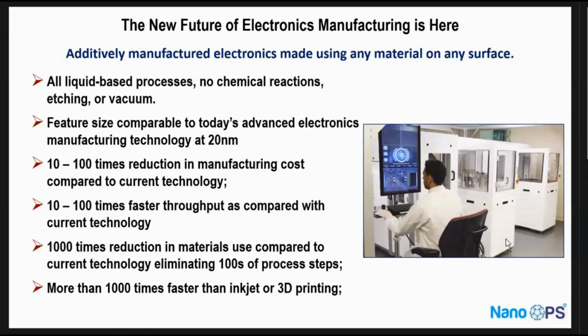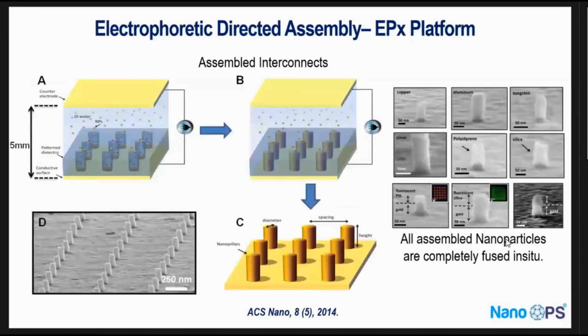It's about 10 to 100 times cheaper. It's about 10 to 100 times faster than conventional fabrication, for example. And it's about 1,000 times faster than typical inkjet or 3D printing techniques. In other words, you can do 1 layer per minute on a 4-inch wafer. For an 8-inch wafer, it will take about 2 minutes. So this is the first technique.